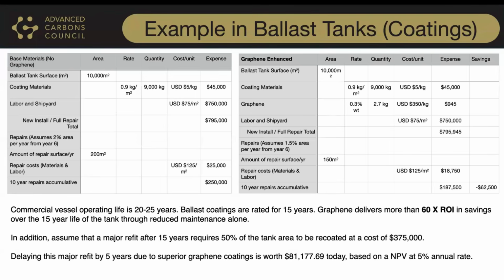Now, once that vessel is underway and working, from year 6, you start to have corrosion problems, and they do spot maintenance. And the assumption here, based on data from the industry, is that about 2% of the total area is going to need to be repainted and spot protected. So that equals about 200 square meters of area that needs to be painted every year from year 6 until year 15. So 10 years of maintenance at about $125 a square meter, because once that ship is launched and you start to do repairs in the ballast tanks, it gets more expensive per square meter. So that's $25,000 a year in maintenance for years 6 through 15, or $250,000 over that 10-year period.